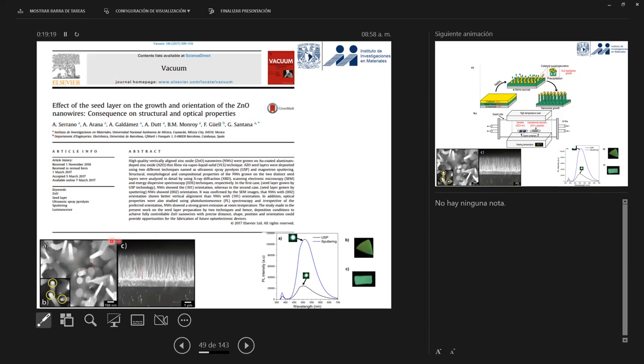Here I am demonstrating that we were successful in growing vertical structures of nanowires. You can see the scale on these SEM images. It is 1 micrometer. In this case, the length was around 3 to 4 micrometers and the diameter was 60 to 100 nanometers. In this inset, you can see something bright on the tip of these nanowires. That was gold. Now I'll give you a brief introduction about this growth technique, but we were successful in growing these nanowires with gold on the tip.